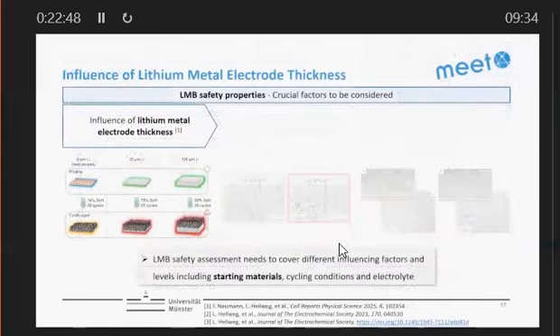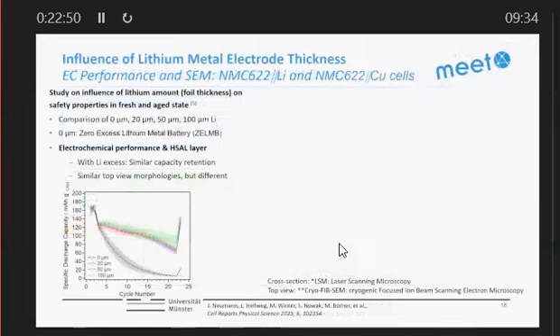Okay. And now we are looking at the influence of the lithium metal thickness. Here we have four different thicknesses: 0, 20, 50, and 100 micron lithium. We see that for 0 micron lithium, that means anode-free, zero excess, after 20 cycles the SOH is at 20%. So the lithium is used up very fast.